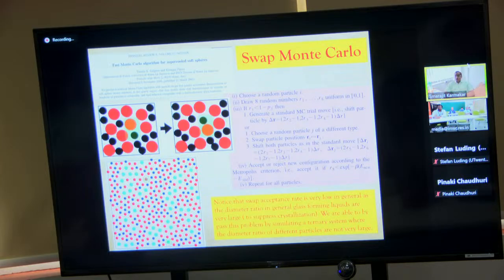This may sound like a very trivial change in the Monte Carlo method, but it turns out to be one of the best ways to speed up the relaxation process. I will show some results soon that just by swapping two particles of different types, this will be useful only if you are dealing with systems which are binary or polydisperse. For example, in a binary liquid, you can take a big and a small particle and swap their positions.